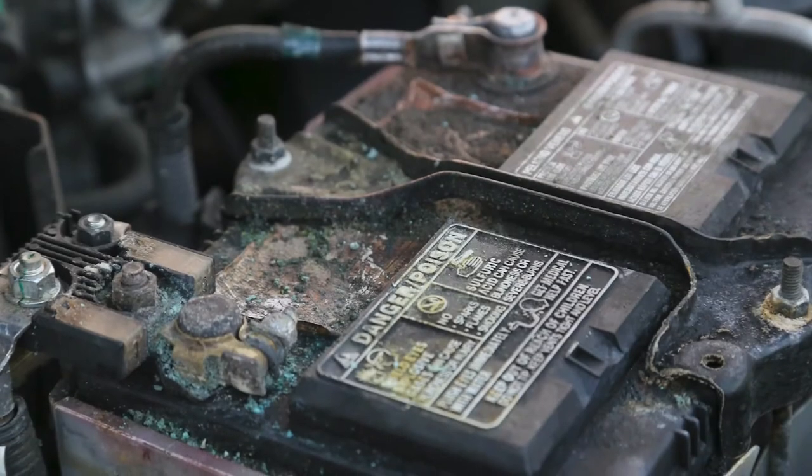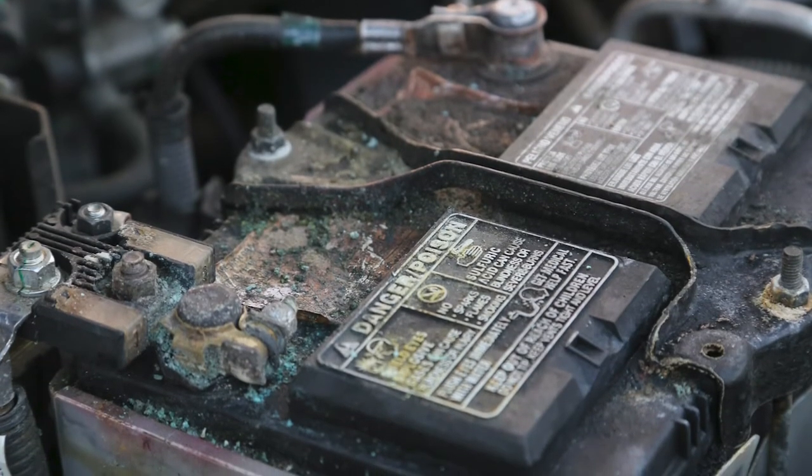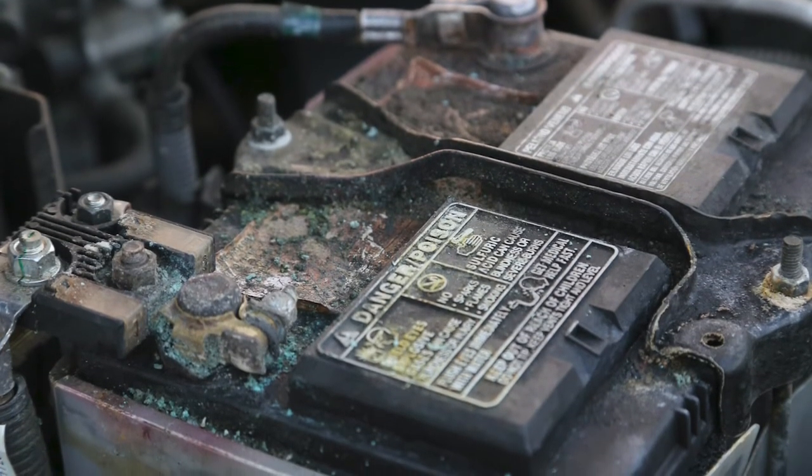There are several negative impacts of underwatering lead-acid batteries. As the water evaporates and the level drops, the top of the battery plates will get exposed to air and oxidize, rendering that part of the plates useless. The remaining electrolyte in the battery will be more concentrated with sulfuric acid due to the unreplaced evaporation of water, thereby accelerating corrosion. During charge, the battery will get excessively hot, further accelerating corrosion of the grids. This will result in reduced capacity and reduced life.